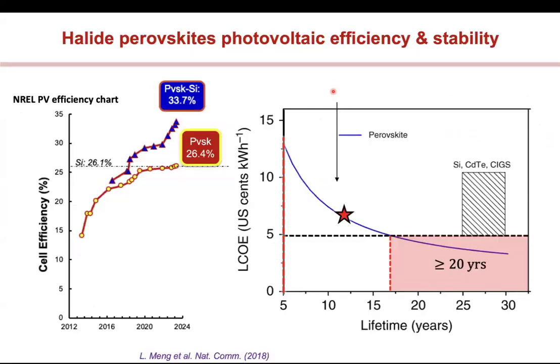Okay. All right. And so how do you do that? In fact, what I'm showing you is this plot, or a derivative of a plot that NREL puts out. It's the solar cell efficiency as a function of years. And you can see that this yellow line here is what has happened to the halide perovskites. And you can see in just about 10 years, the efficiencies have surpassed that of silicon, right? And so that's been amazing in terms of just a materials platform. For example, for silicon to get to 26%, it has taken something like 40 to 50 years. Right. And that's happened for perovskites in about 10 years. So that's been remarkable, and that's attracted a lot of attention.